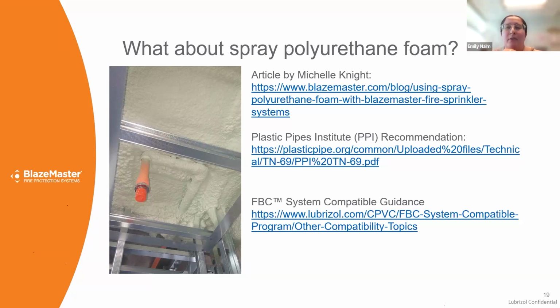And just as a side note too, when you're applying polyurethane foam, it can get up to 300 degrees or more in the foam. So just put it in thin layers so the heat can dissipate, and put expansion loops if you need to.